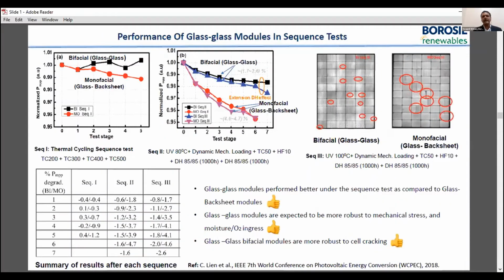Yes, definitely. I have one example where sequential tests were carried out, and what they did, they took monofacial as well as glass bifacial modules. Monofacial is typical glass to backsheet. They did sequential tests, the first being the thermal cycling sequence test, the second being UV plus dynamic mechanical loading, and the third being a more severe version of sequence 2.